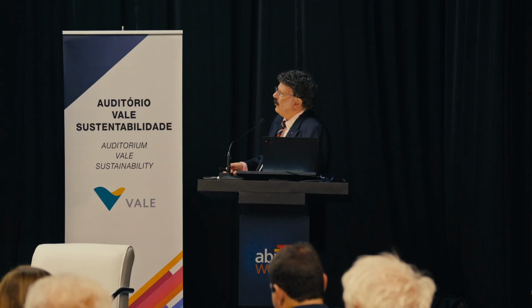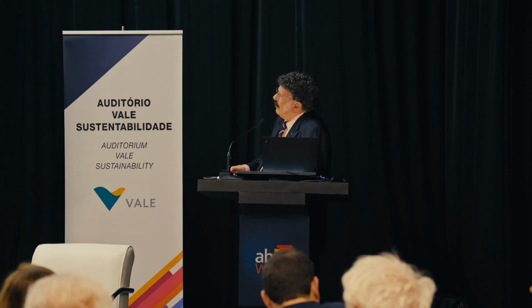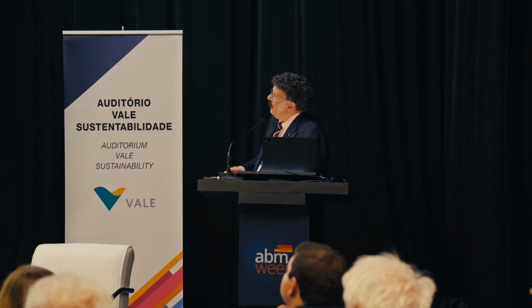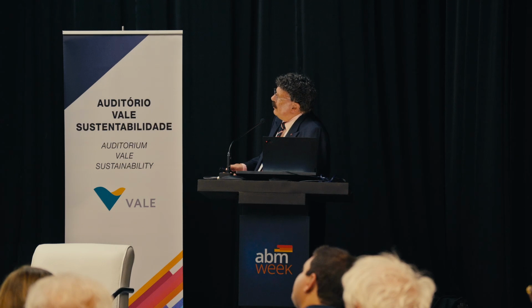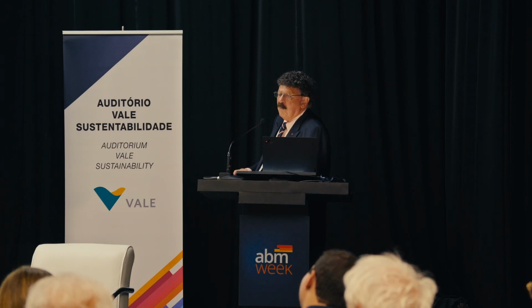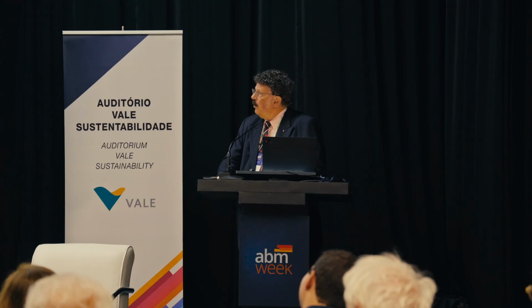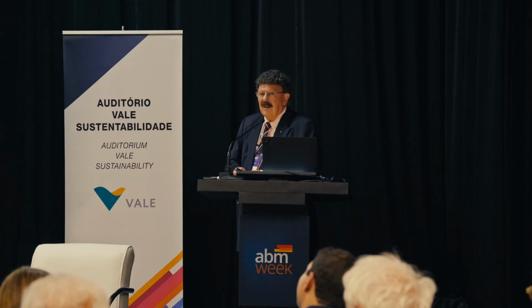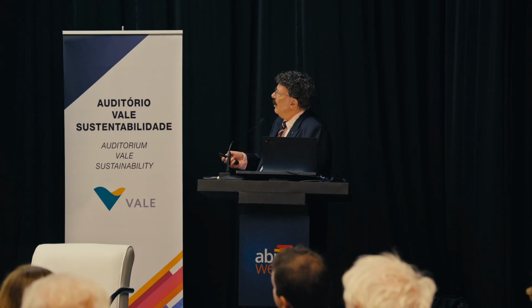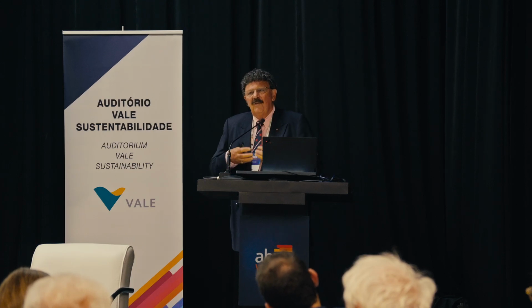These are toughness curves, toughness versus crack extension. Red is room temperature, this is lower temperatures, and this, of course, is the temperature of liquid nitrogen. This was the original Cantor alloy. That's the one I've been talking about, or at least a version of that. It gets tougher at lower temperatures. But when I start to use too much transformation toughening, you can see we still get good toughness, but we don't see the very high toughness at lower temperatures. So too much transformation-induced plasticity is a bad thing.